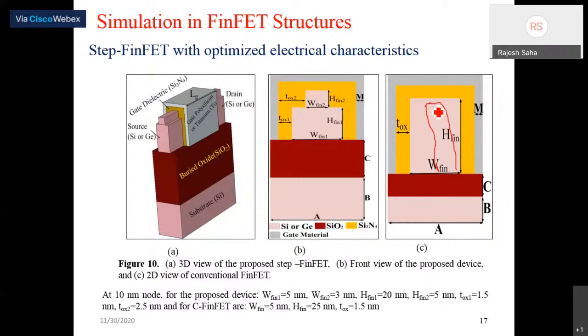In order to overcome this, we have proposed a new structure. As you can see, this fin looks like a step, and we name this FinFET the step FinFET. We have observed a significant reduction in the off current, but the on current is not reduced by that significant an amount compared to the conventional FinFET.